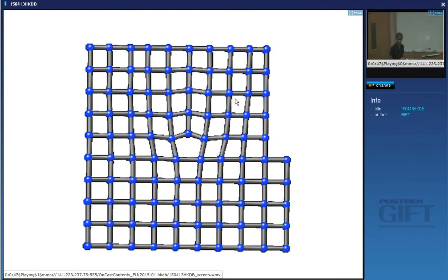Well, this is a dislocation, right? And you have an extra half plane. And that extra half plane means that the planes near it are tilted like this, exactly as in the previous slide. So if you put an array of dislocations, then that fills up that empty space we had in the first slide. Okay? So dislocations correct for that space, and therefore, in the tilt boundary, we should be able to see dislocations when we look down a transmission electron microscope. Okay?